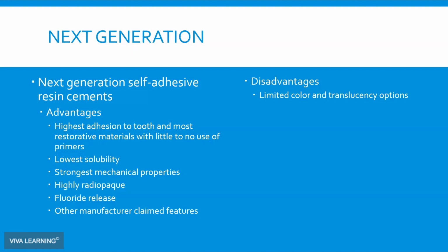Now, you'll notice the list on the left is essentially the same as the resin cements. However, the first category that I identified, this high adhesion to tooth and most restorative materials with little to no use of primers, is a significant departure. For example, bonding to zirconia does not require a primer. You can certainly use one. In fact, I do, but for different reasons.